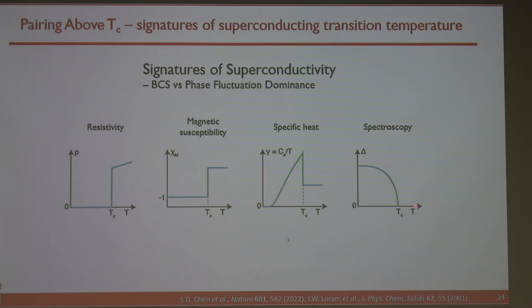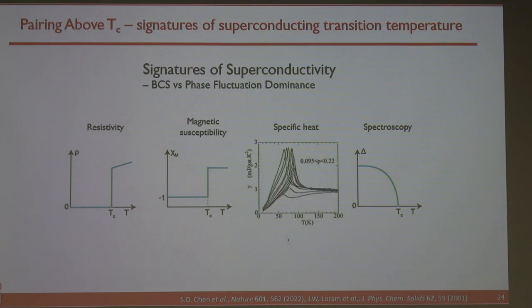And also in BCS, there's an energy gap that turns on at TC. In the cuprate case, this happened in 1986, and this happened somewhere around 89, 90. So they are all 25, 30 years ago. But the spectroscopy part remains a puzzle. We saw the gap measured. Now we are sure that gap indeed is superconductivity, but it does not tell you the global TC. And the question is, what is the physical quantity that has a singular behavior at TC?